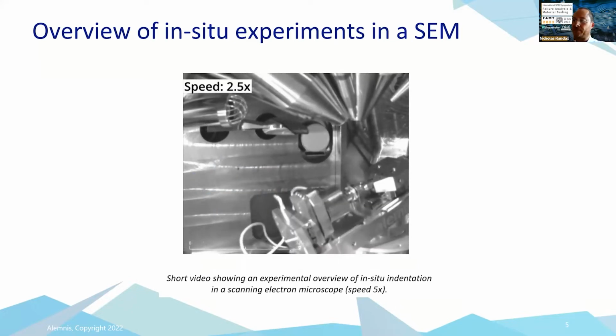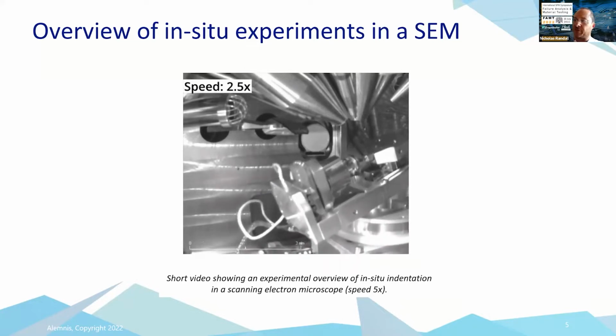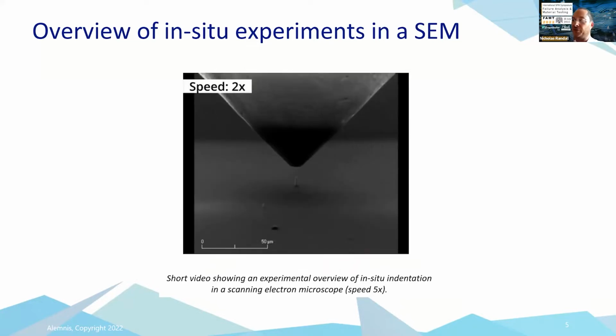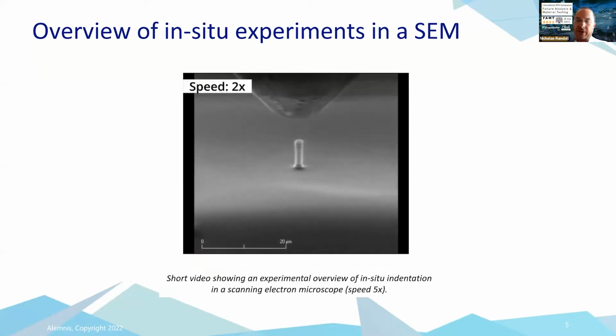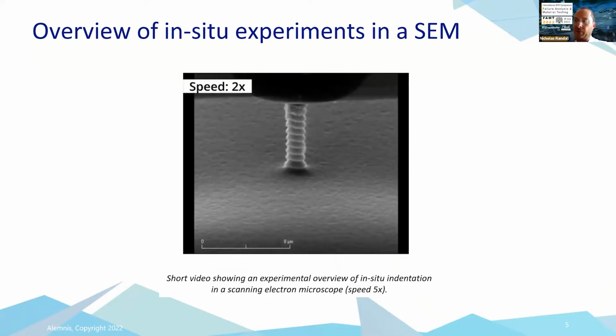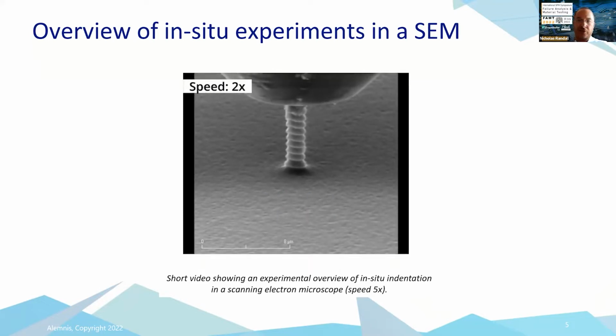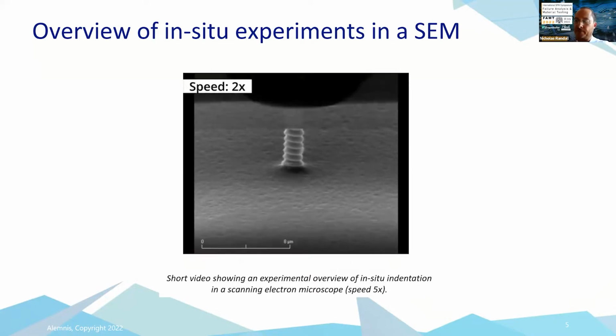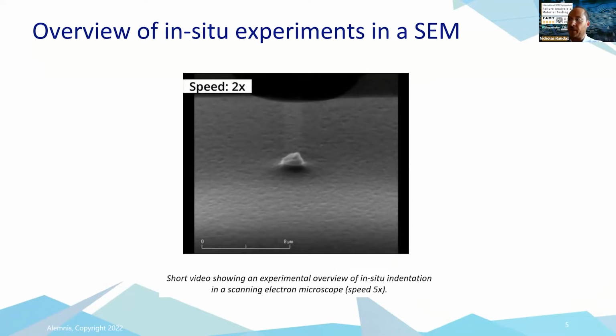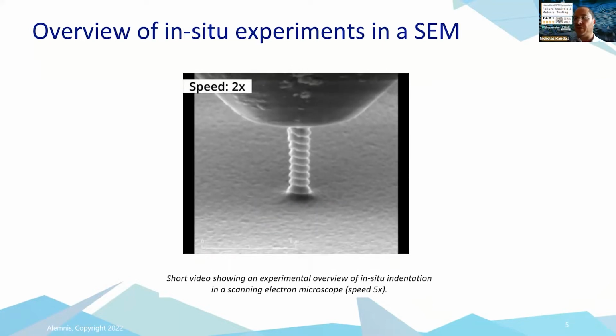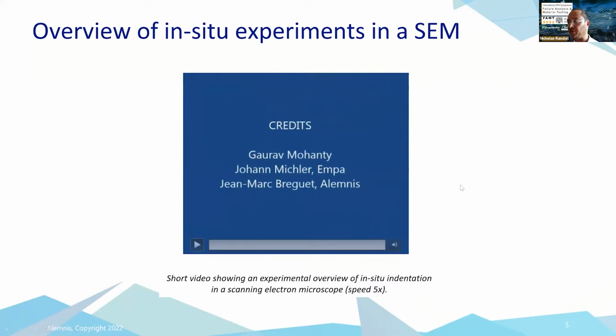Here we go. Once we're focused on the surface of the sample, we can then choose where we want to make a test. In this case, we're looking at a micropillar that's been made by focused ion beam, so a FIBed pillar. We might want to do a single cycle stress strain analysis to see when the pillar breaks. This is a silicon micropillar. Okay, there it goes, it breaks. Or we can program the system to do whatever we want. In this case, we're doing a fatigue test. We can do this low cycle, high cycle. We can choose the amplitude, etc. So you get an idea of how the system works.